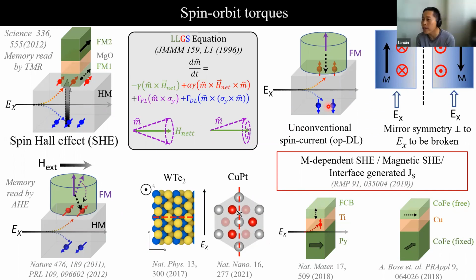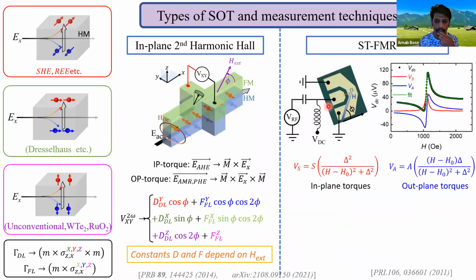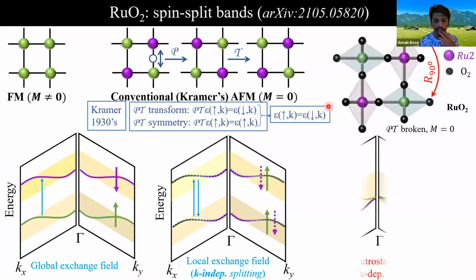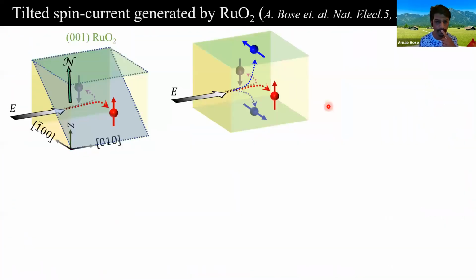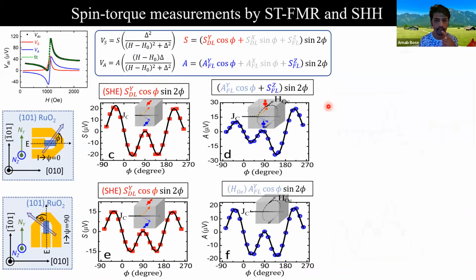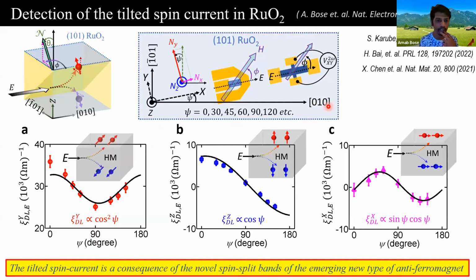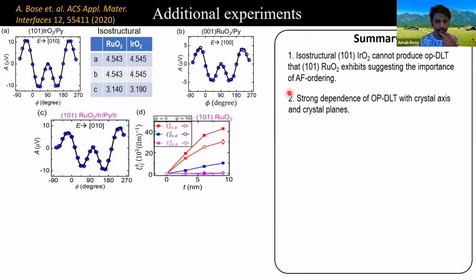Thank you. And one more question: what is the spin diffusion length in this material? Exactly, I have not calculated it, but we did a bit of thickness dependence of ruthenium dioxide. From that, we can speculate some number, but we have not done a very detailed thickness dependence. It will be around 6 to 7 nanometers. I'm just roughly speculating from this curve.